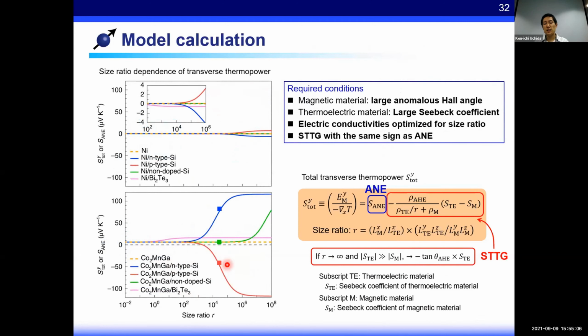Actually, in STTG, the total macroscopic transport properties of the thermoelectric material are important. The topological band structure is not directly related to this phenomenon. But if the topological band structure contributes to exhibiting a large Seebeck coefficient, which is important for the STTG, then it matters. So here we also assume bismuth telluride in addition to silicon.